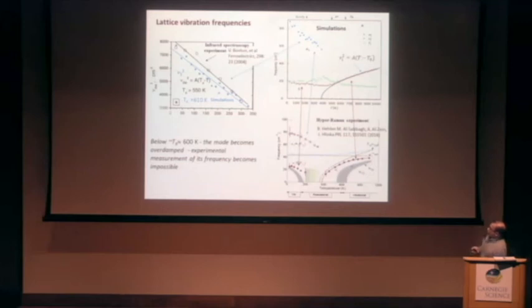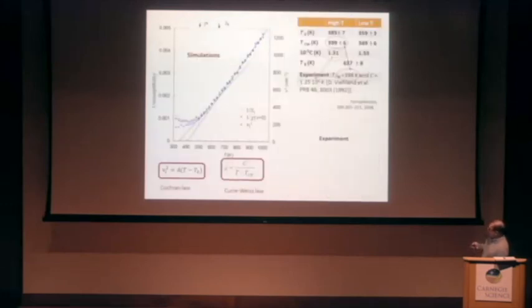Thus, one more important point is that below Burns temperature, this phonon mode becomes overdamped according to experiment and according to our simulations. This means that in the interval between 200 and, say, 600, it cannot be measured reliably. But in our simulations, we can find the temperature dependence. And if we look at the temperature dependence of this soft mode, nu squared is the crosses, and the symbols are the reciprocal susceptibility.